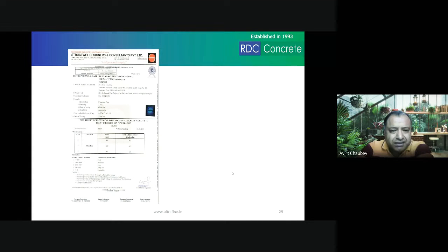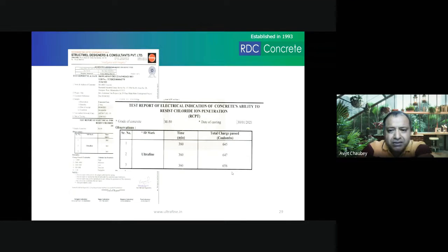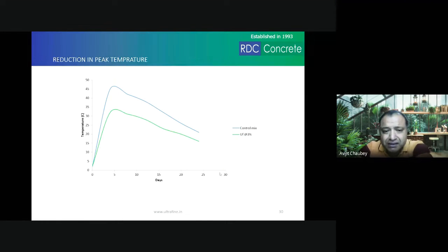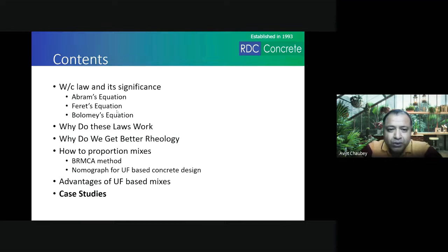These are the results from the third party structural, right? So just the magnified view of this. The RCPT value that we have been able to get is 645. This is the heat of hydration test that we have done. Now this is not for the same mix. This is for the same strength at 28 days, so the mix is different for both these graphs. This is the control mix without ultrafine. This is the mix with ultrafine for the same strength, at 3% ultrafine. And you see the temperature is much less as compared to control concrete.